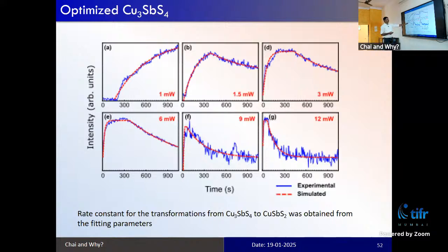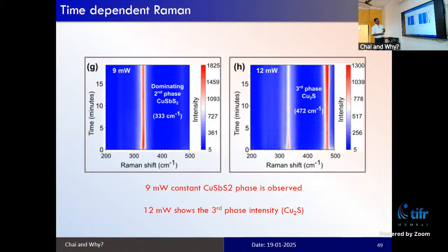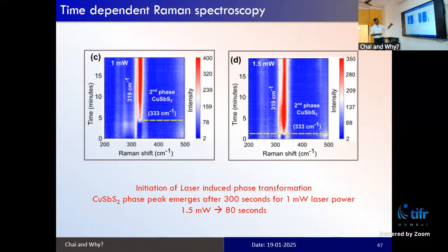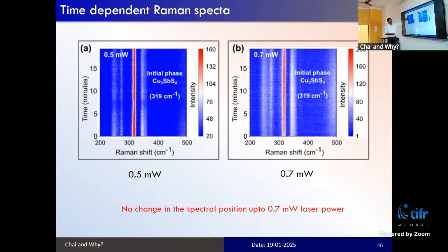So, what is the rate constant of this? We have determined how much energy is required to initiate this phase transition process. So, what we have done is time-dependent Raman spectroscopy. For example, at the initial phase, even if you shine light, for example this is 0.5 milliwatt, even if you shine this light up to 1000 seconds or 20 minutes, there will be no change in the material system. For 0.7 milliwatt also, there is no change in the material system.